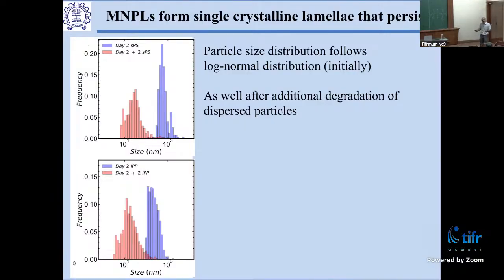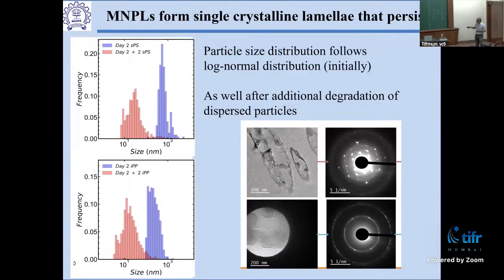This is something I sort of alluded to earlier, is that as these things continue to degrade, effectively, you get these crystals. Now, these crystals, I told you, form these sheets, lamellar sheets. You basically get these crystalline sheets, and over time, you break off the connections between the sheets. You break off the tie molecules, and eventually, you end up with only these sheets. I'm not going to go into why they are log-normal distributed. But eventually, what you see is you end up with essentially single layers of these sheets, which are crystalline, and you can then look at electron diffraction to really see that these are crystalline objects that you get in here.